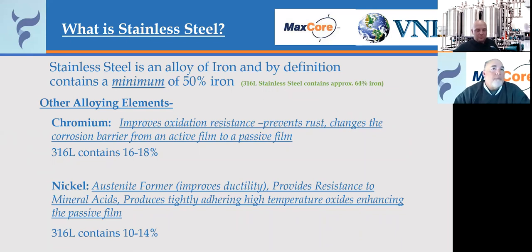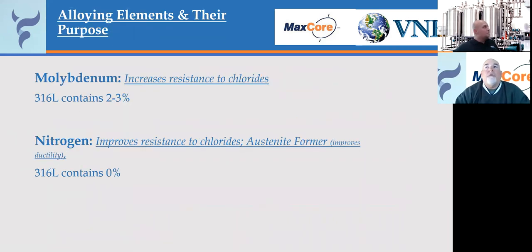Nickel is an austenite former. It provides resistance to mineral acids. It causes that passive film to become tightly adhering on the surface of the steel. Molybdenum provides resistance to chlorides. 316L has 2 to 3% content. Nitrogen is an austenite former. Typically 316L has 0%, but our 6-moly alloys do have a percentage of nitrogen in them, so that enhances that.